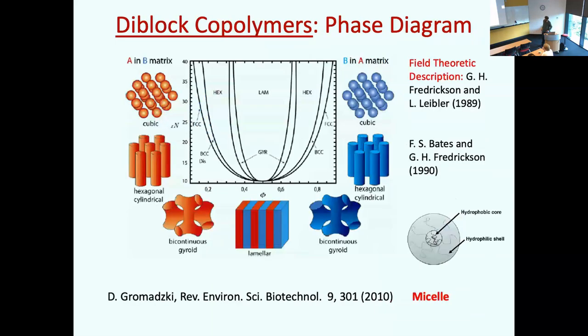Another example, again, without going to details, you take 2 different kinds of copolymers, mix them, A-rich and B-rich, and here is the number of monomers times some polymer-dependent quantity, and you get this beautiful zoology of structures from lamellar to face-centered cubic to hexagonal close-packed, bicontinuous gyroid, double gyroids, last space group number 230. And again, using some topology and some kind of field theory, you can actually reproduce this phase diagram beautifully. This is a nice article to read about it. I'm not going to go much into detail, just to give vignettes of what is possible.